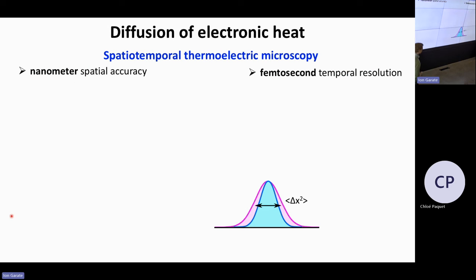So what we're going to do here is spatiotemporal measurements. We're not just going to look at energy dynamics, but also at how this energy dynamics changes when you change the spatial offset between the pump and the probe. That's going to give us access to diffusion.